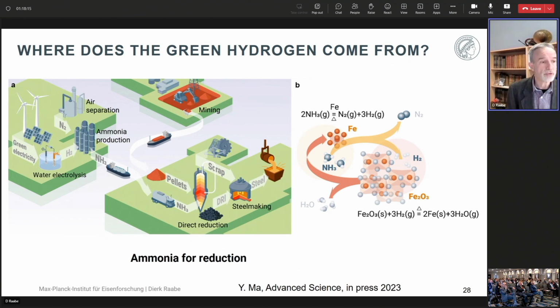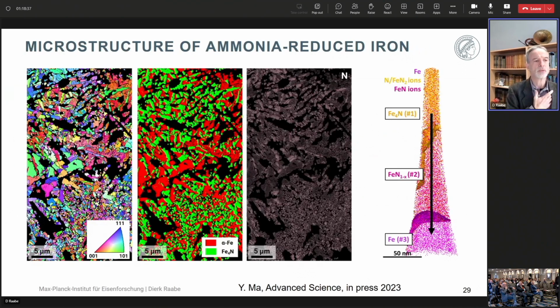And it could therefore be interesting to also blend ammonia in, which is a 180 million ton traded chemical. And so we did that. We used ammonia for direct reduction, and it works. The paper is now finally accepted, in press at the end of the month. And so what happens is you have first an ammonia splitting into hydrogen and nitrogen. That is typically happening around 420 degrees in equilibrium, but due to the iron acting as a catalyst for ammonia splitting, that is well known, you produce it already at 350 degrees centigrade out of the waste heat.